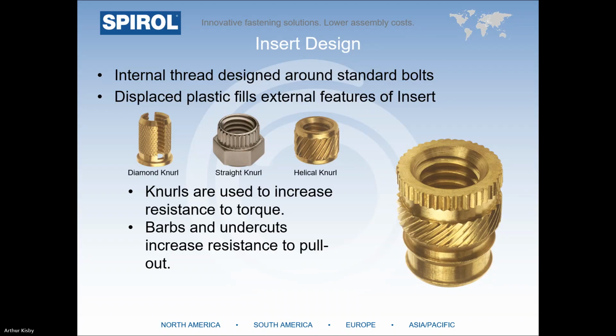The reason being is that if you press a diamond knurl part into plastic, the diamonds literally shred the plastic during insertion. The most popular type of insert where diamond knurls is found is on what they call an expansion style insert, here in the upper left. As you can see, there's a slot on both sides of the insert. You push it in the hole, the slot closes. As the bolt is installed into the insert, the bolt makes the slot open up. The diamond knurl is supposed to bite into the wall, but in reality, the performance is pretty low and the cost is much higher. SPIROL has since replaced the expansion style insert with a press-in style that have much higher performance and a much lower cost.